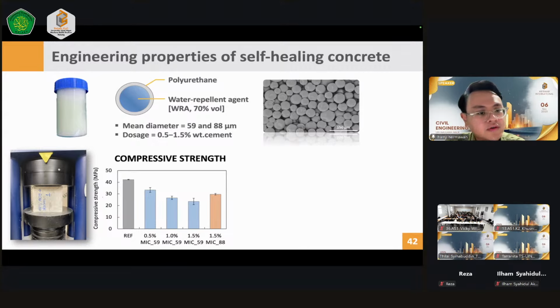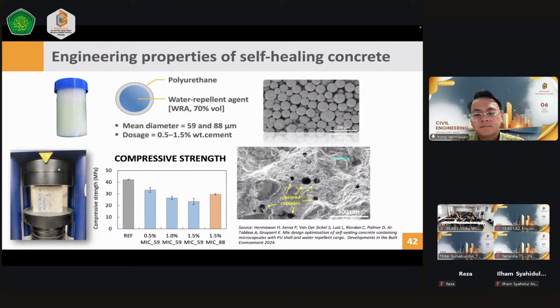You also have to go into the microstructure of your concrete. By using scanning electron microscopy, we can evaluate the condition of our concrete matrix. In this case, I found that there were several ruptured capsules within the microstructure, within the matrix. And these capsules remain within the matrix and act as defects, as pores or hollows. Due to these big pores from the microcapsules, eventually it will affect the mechanical properties of the concrete. That is why the concrete made with the microcapsules shows a strength decline.